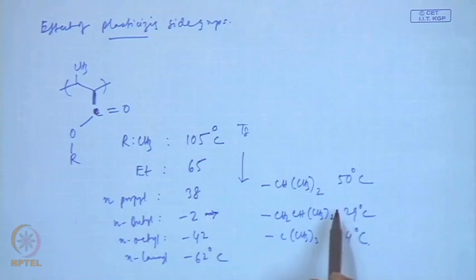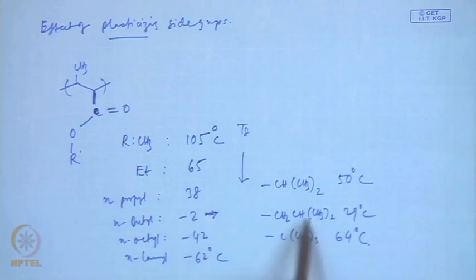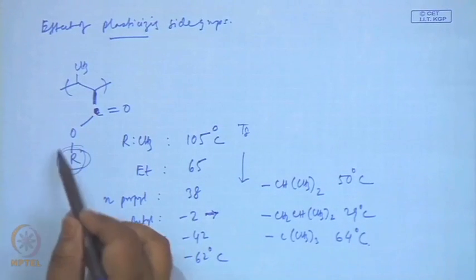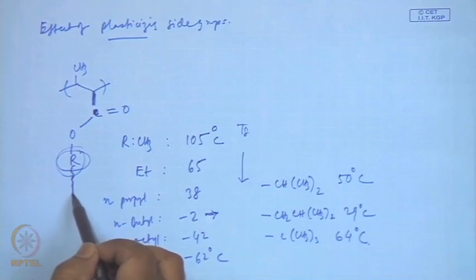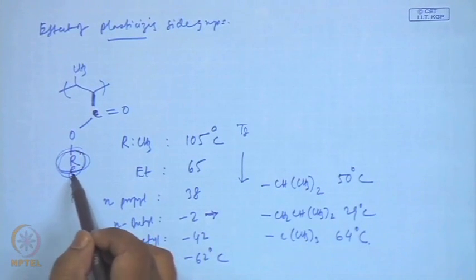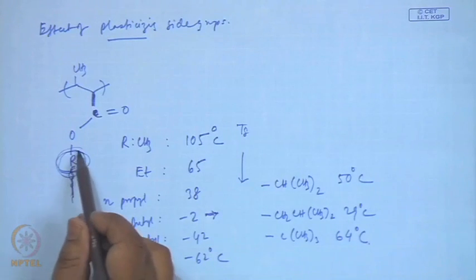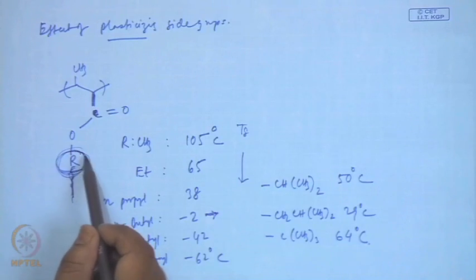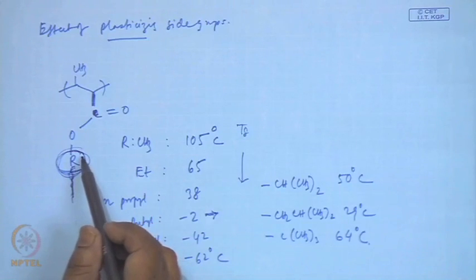So, look here, when you have the isobutyl and tertiary butyl groups, they are becoming bulky in this way, whereas the N propyl groups are increasing in size along a chain. So, the free volume because of this long chain is much more compared to the free volume produced by bulky groups having a spherical or coil type shape.